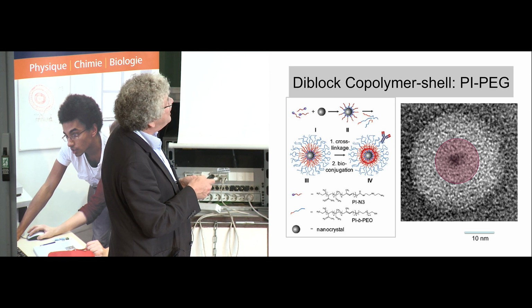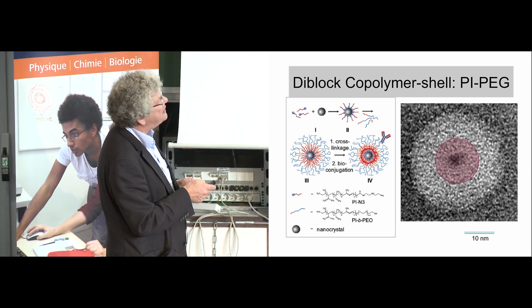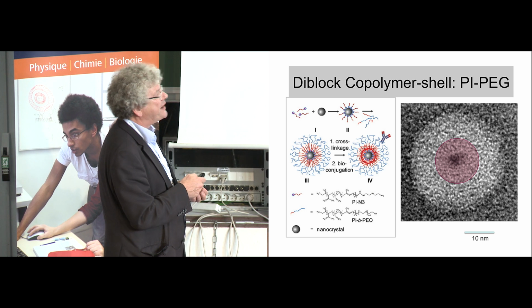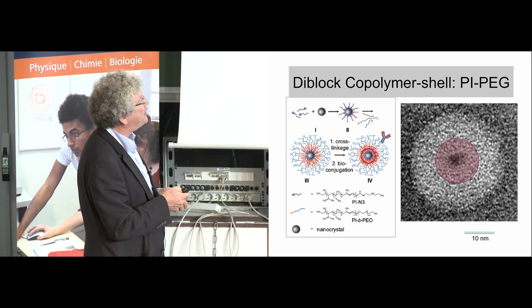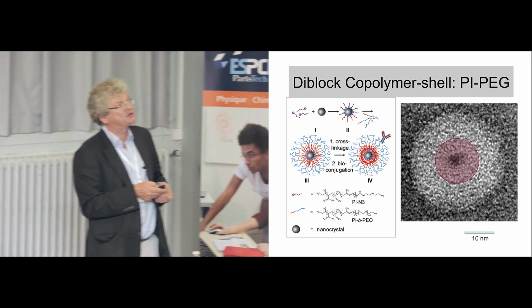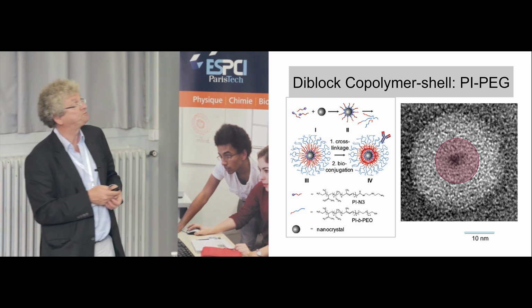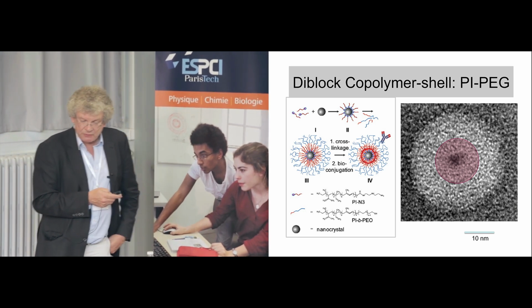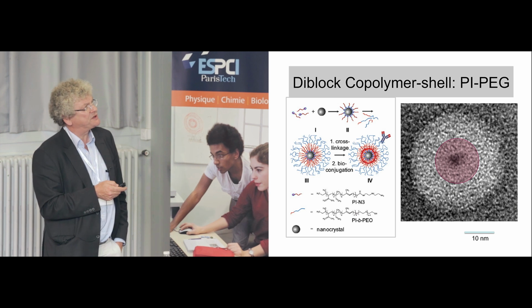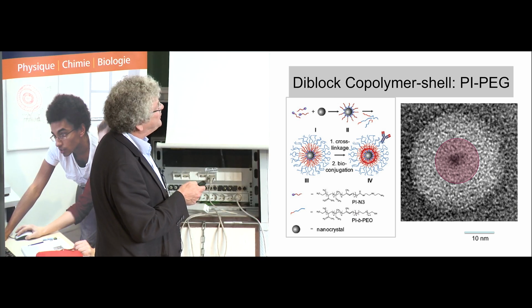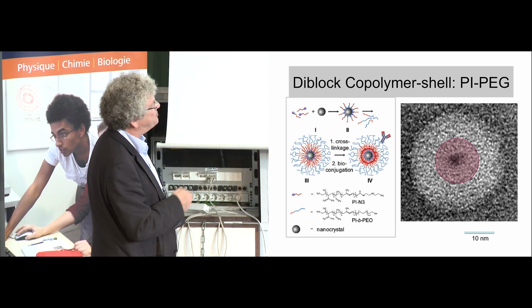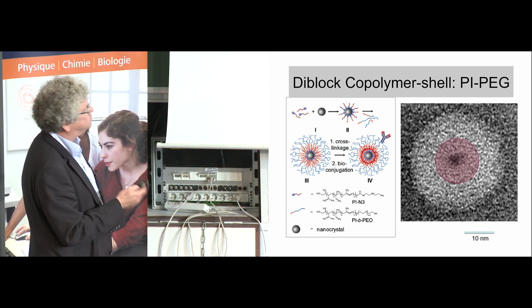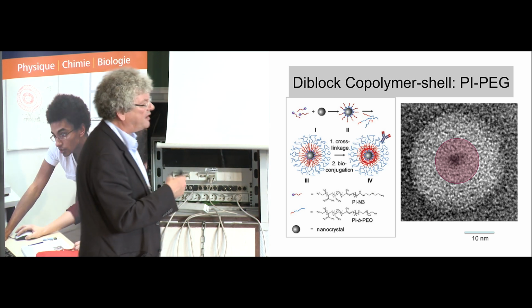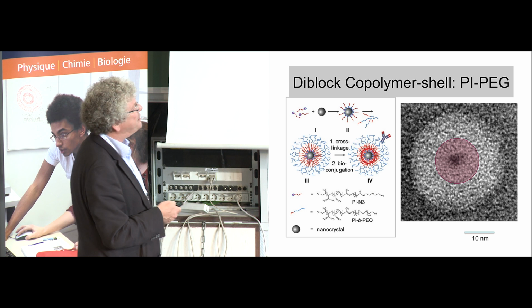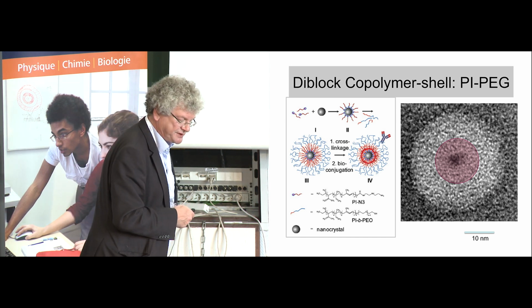And so at the outside, we can also functionalize it with any kind of organic molecules which allow further linkage to something like sugars and things like this. Okay, so here is one of these particles, quantum dot encapsulated. This is the polyisoprene part, and this is the PEG part here. It sizes 25 nanometers up, depending on the exact size and conditions.